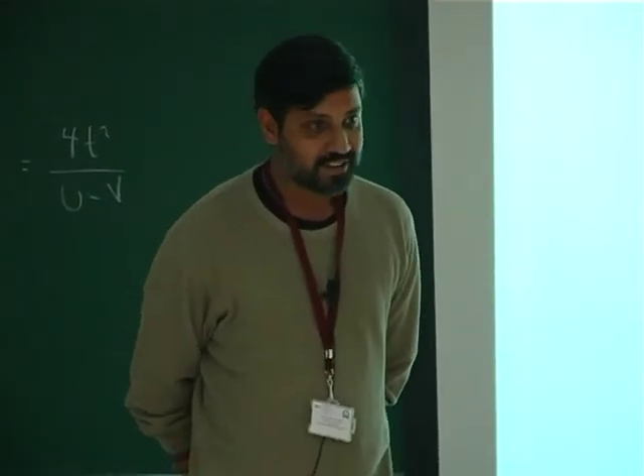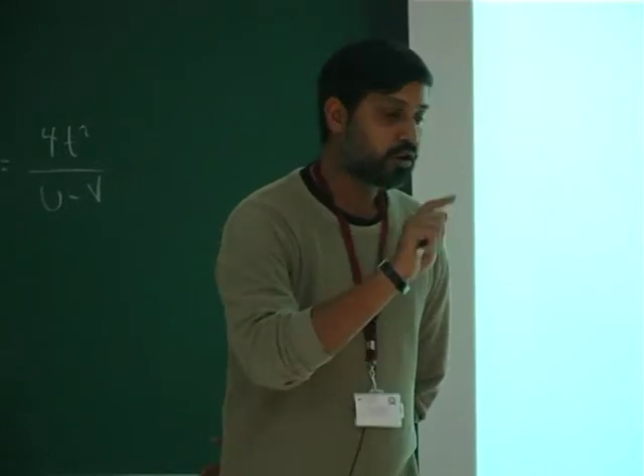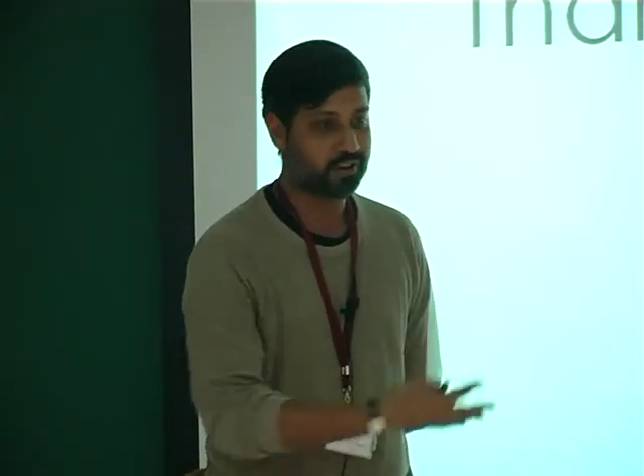Are there metallic systems that have oxygen holes? No, not a metallic system. It has a gap, but it's very small. I have done photoemission studies. It looks like a very soft gap. Her calculation actually gives a band gap of something like only 0.1 electron volt, not more than that. In principle, yes. I have not tried. These are possibilities which we are actually looking into. This is a very fresh thing. I have not even communicated anything.